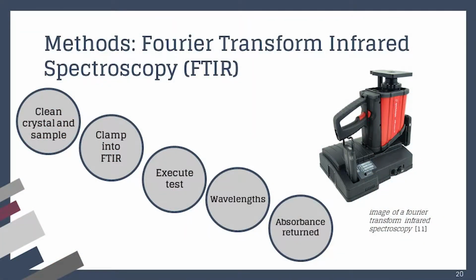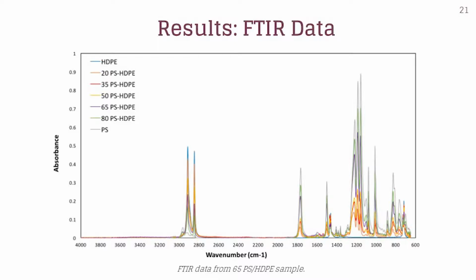Next, we clamp the sample into the FTIR, and this ensures that the sample is held directly on the crystal for analysis. And then we execute the test, which consists of the FTIR shooting various wavelengths of light through the sample, and what it returns is a graph of the absorbance at various wave numbers. Here are our results from each of the composites that we tested. We overlaid them, so this is all of our data from the FTIR.